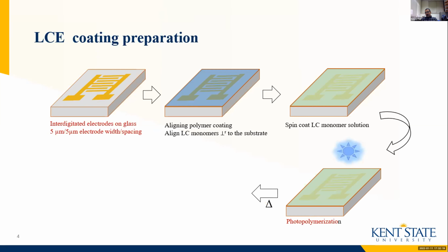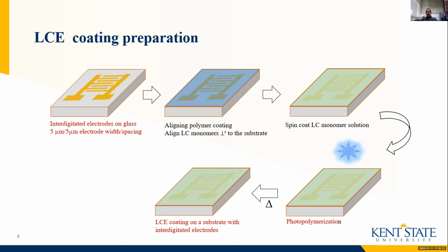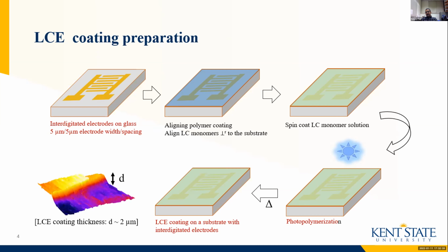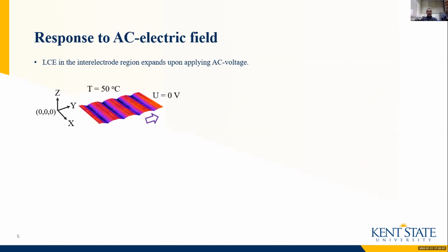We heat it to evaporate the residual solvent left during polymerization. We have finally a liquid crystal elastomer coating on the IDE substrate, the interdigitated electrode substrate. We measure the thickness of our coating to be about 2 micron. We would like to study the effect of an in-plane AC electric field on our elastomer coating.